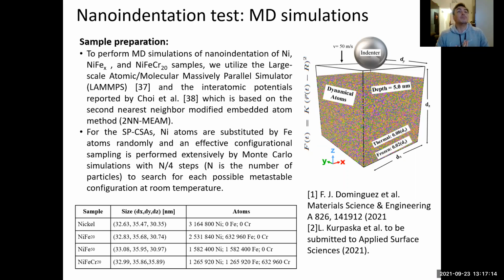So now, how to prepare the sample? Since I don't know how to prepare a bulk metallic glass and this mixture that is extreme, my friend René and I carried out this study to perform MD simulations with Monte Carlo. For the nickel, we are taking the original nickel sample, then we are substituting some nickel atoms by iron atoms, distributing randomly, taking a nickel atom, putting an iron atom to reach 20% of iron or 50% of iron. Then we are also preparing the other sample, which is nickel, iron, chromium. So again, you take some nickel atoms and then put iron, take nickel, put chromium.